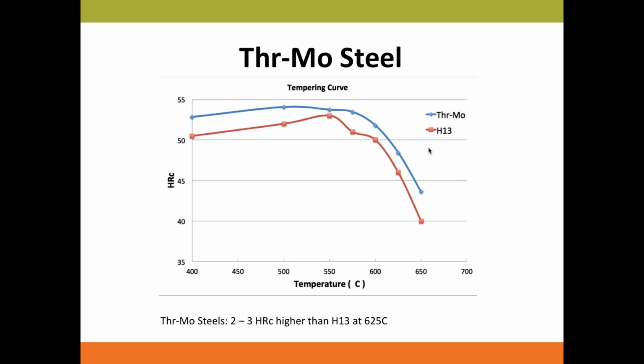So the end result is we can see the tempering curve. The tempering curve usually means when you try to temper or soften the steel. The red one is the H13. The blue one is the newly modified Thr-Mo steel, which belongs to Castor proprietary steel. You can see from 400 degrees Celsius to 650, it's all around 2 to 3 Rockwell higher. So using that 2 to 3 Rockwell higher and also the heat checking, toughness and wear resistance index, we can have a pretty good idea. Compare two steels with the other conditions identical, what can you get from the steel?